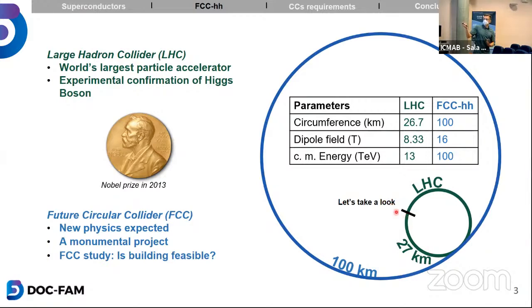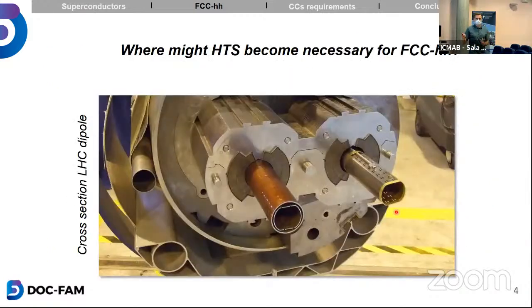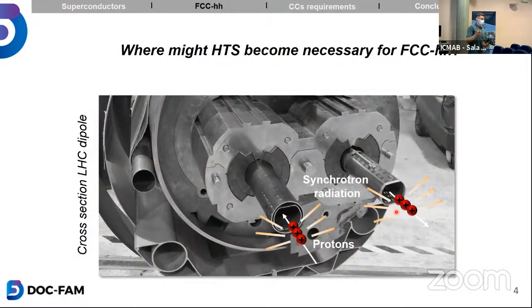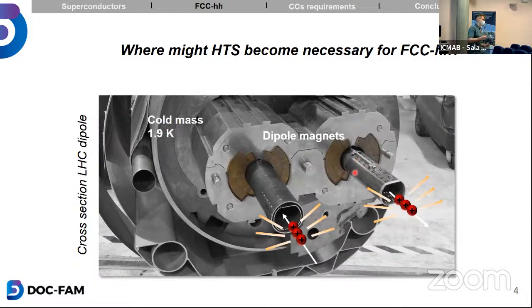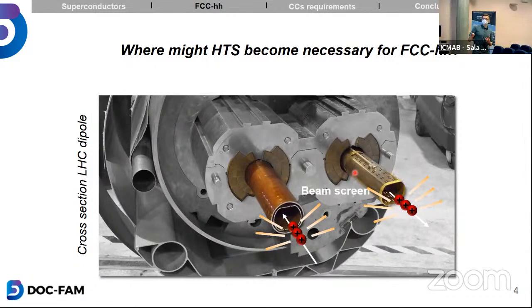For this, we have to take a look at the cross-section of such a particle accelerator. If you want to collide particles with each other, you need to accelerate them in opposite directions. Since they are on a circular track, they will emit synchrotron radiation, which is problematic because you have these steering magnets in its vicinity, which are held at very low temperatures. So if you irradiate them with the synchrotron radiation, they will heat up too quickly, quench, and get damaged. To prevent this, engineers introduce these stainless steel beam pipes, which are called beam screen chambers. Okay,